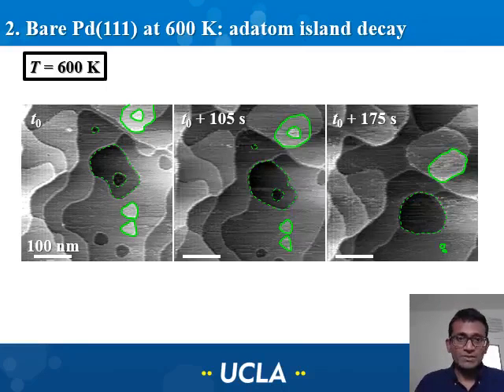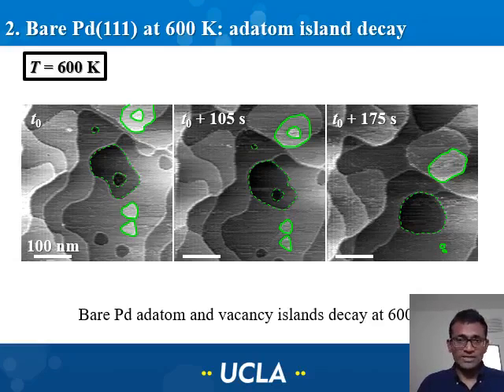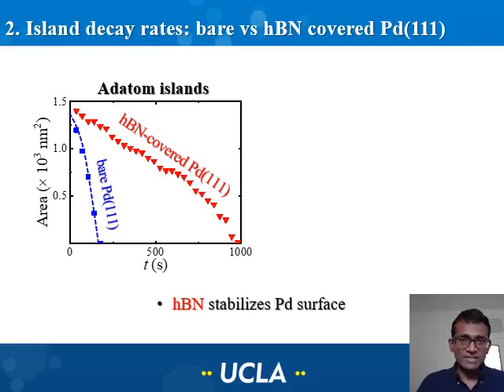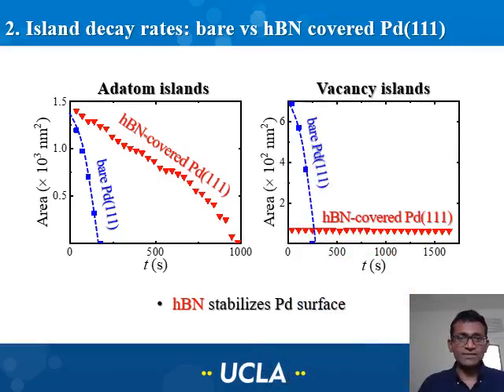If you take in comparison bare palladium, we observe both vacancy islands, highlighted by these dashed lines, and atom islands disappear as time progresses. Okay, no surprise here. But then if we plot the rates of decay of the atom islands and the vacancy islands for bare palladium and hexagonal boron nitride covered palladium, we find that the decay rates are significantly higher when the surface is clean and not covered with hexagonal boron nitride. And in the case of vacancy islands, it appears that the vacancy islands are extremely stable on hexagonal boron nitride covered palladium, meaning the hexagonal boron nitride stabilizes the surface.